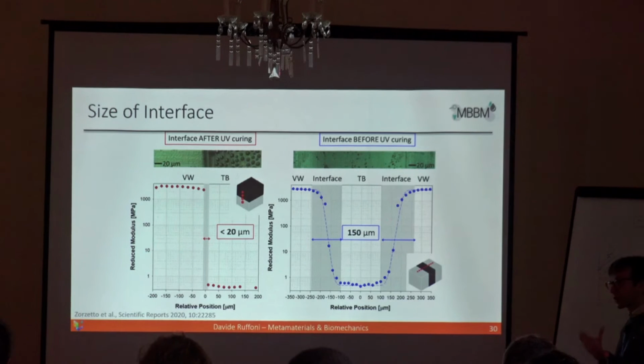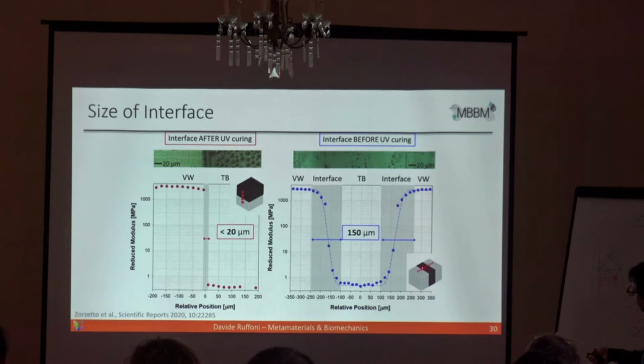The manufacturer of the printer declares the nominal voxel size. Whereas if you indent an object where the interfaces were formed before UV curing, so we design a system like this, having a stiff voxel, soft voxel, stiff voxel, and then we indent it, what you see is a much broader interface transition, up to 150 micrometer, which is much larger than the nominal